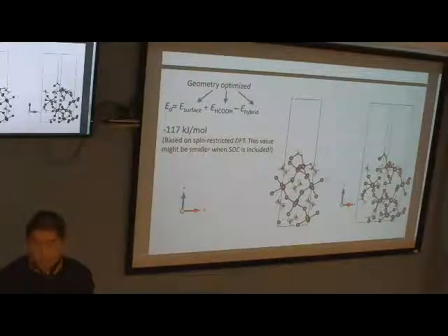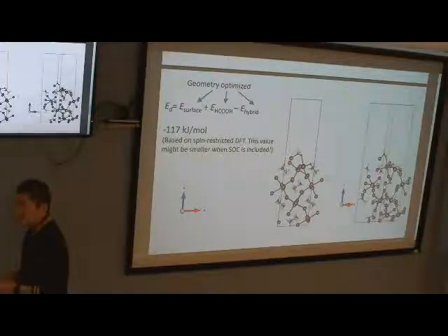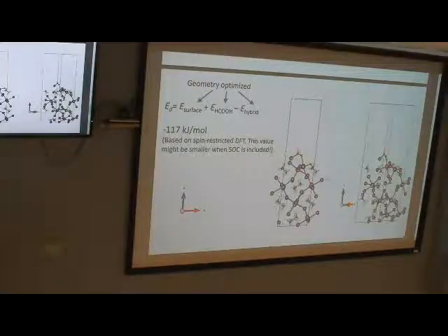Basically what I did right here is I have this molecule and I artificially break it into different fragments and attach different fragments to the surface. Compare the binding. Right. Okay. So it's not the most right and best way, but it is the quickest way. It's like 100,000 times quicker than other things. Okay.